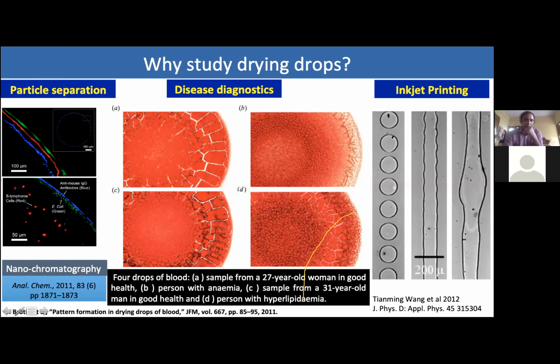The top is an image with model particles, and the image at the bottom is an example where you have a mixture of biologically important particles and molecules, where again a similar concept of size-dependent separation has been demonstrated. The second example, in the center, is disease diagnostics, where A and C are images of a person without any disease condition, and B and D are a case where there is some disease condition. As you can clearly see, the evaporative patterns remaining after the evaporation of the blood plasma are very different, and one uses such simple evaporative patterns as diagnostic tools in this literature.